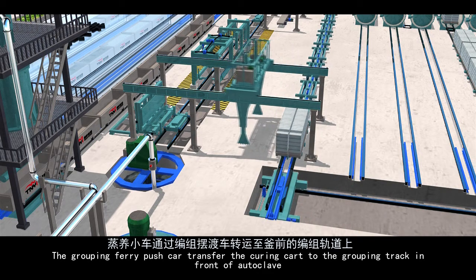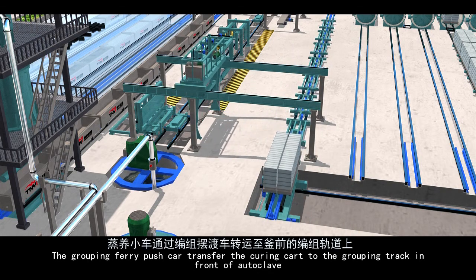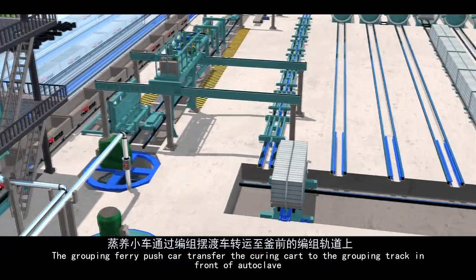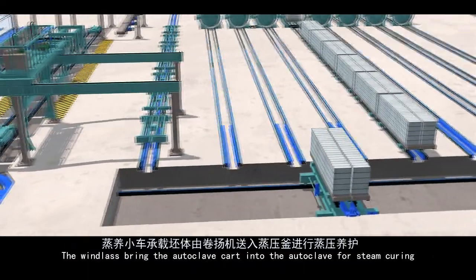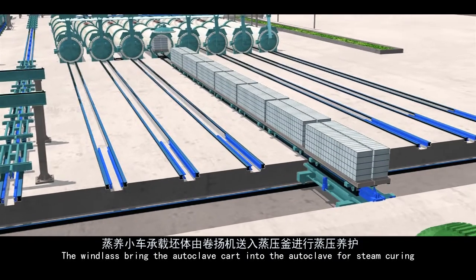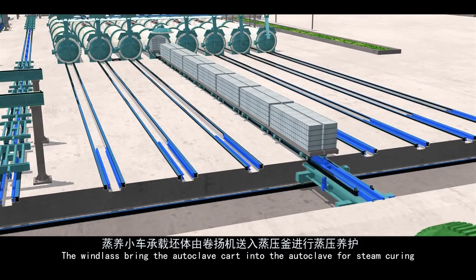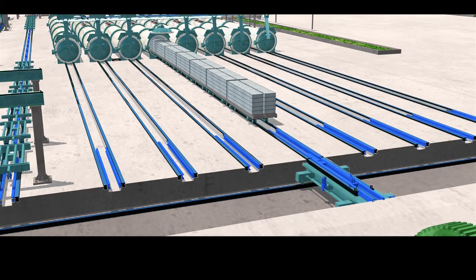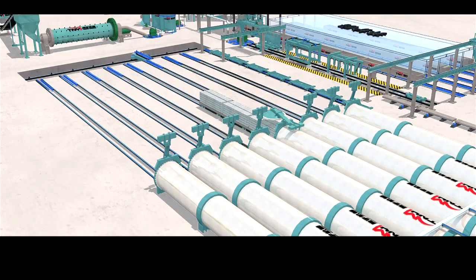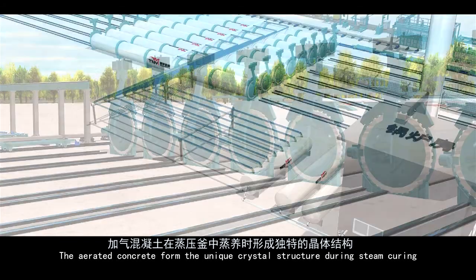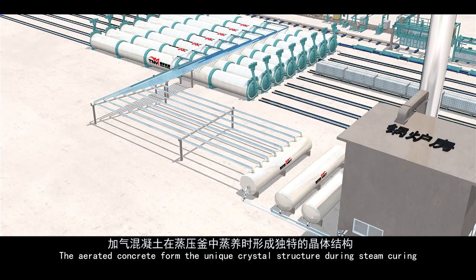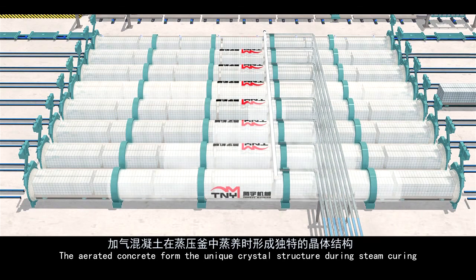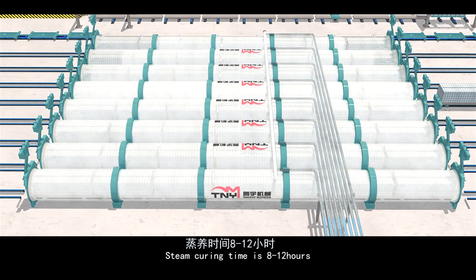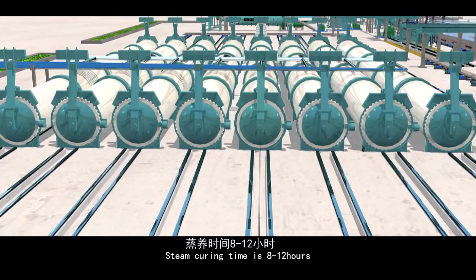The grouping ferry pushcart transfers the curing cart to the grouping track in front of the autoclave. The windlass brings the autoclave cart into the autoclave for steam curing. The aerated concrete forms its unique crystal structure during steam curing. Steam curing time is 8 to 12 hours.